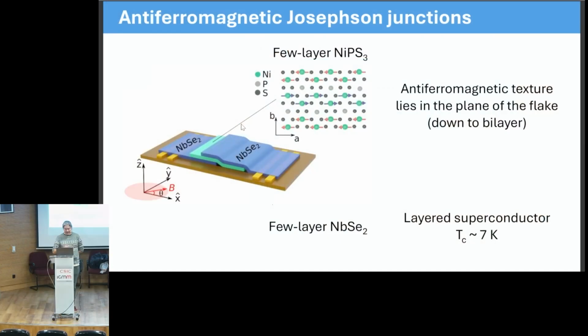The thing here is that this intermediate layer, the magnetic layer, is insulating. We have characterized this, so it's not really like you have a charge density. It has a sizable band gap, and we're measuring this at 10 millikelvin base temperature. So I don't think it's really forming all around, but it's really forming two spots. When we do this rotation, we can infer that there are really two localized spots.